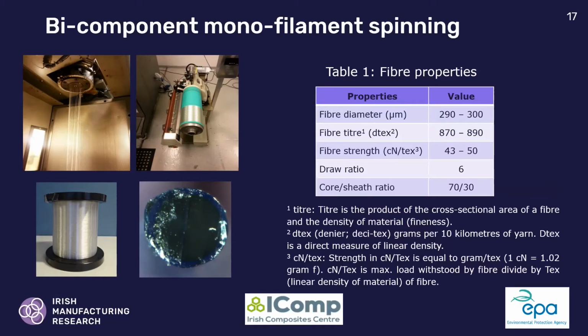It's a research center where they have the facility to develop this bicomponent fiber, as explained in the first material characterization. Before this process, we have to combine the PETG and PBT, which is carried out using a twin screw extruder. So we blended them in the extruder and produced the filament, and then the filament was converted into pellets. These pellets were taken to Belgium to make a bicomponent. So the core will be 100% PET, and the sheath will be the blended pellets of PETG and PBT.